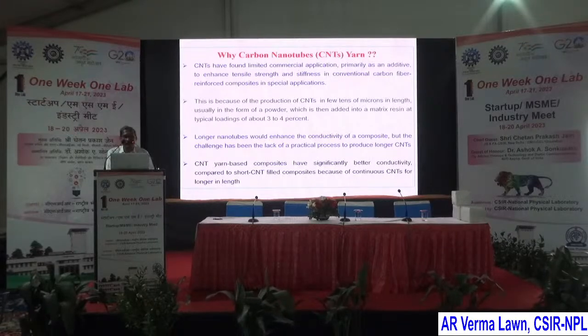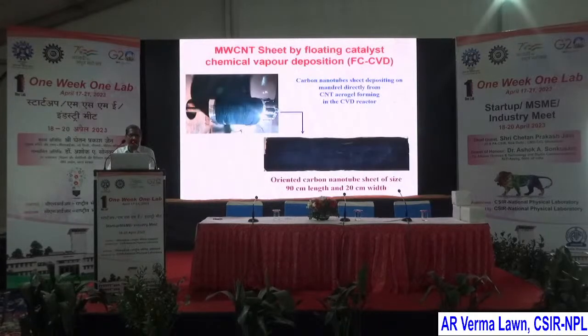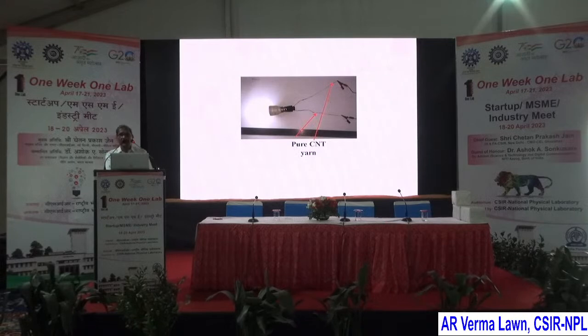So NPL has developed this technology for making multi-wall carbon nanotube sheet by a floating catalyst chemical vapor deposition technique, and that sheet is collected on the mandrel, and it is almost 1 meter long. In this case, most of the carbon nanotubes align in one direction. So this technology has been developed in NPL, and you can then spin this carbon nanotube paper further. We can get thread-like material having conductivity as good as our copper wire.